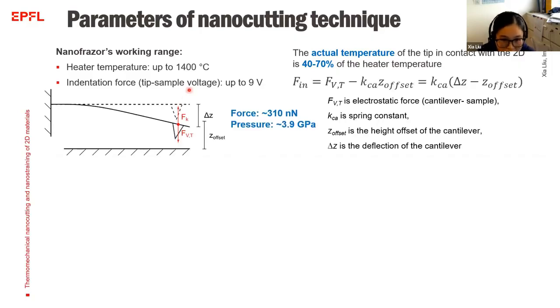So you can see when we apply the voltage to the piezoelectric cantilever, it will bend, and there is also the spring constant. The spring constant will prevent the cantilever from bending. So in the end, we can get the indentation force from these two values. Based on our calculations, the highest force we can achieve is about 300 nanonewton, and the highest pressure we can achieve is about 4 gigapascal.